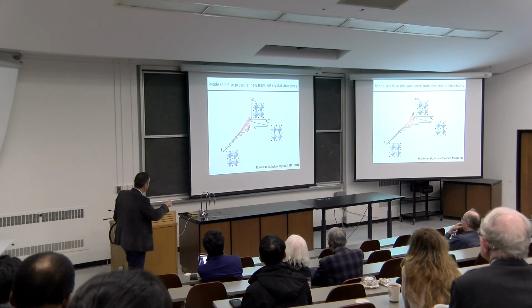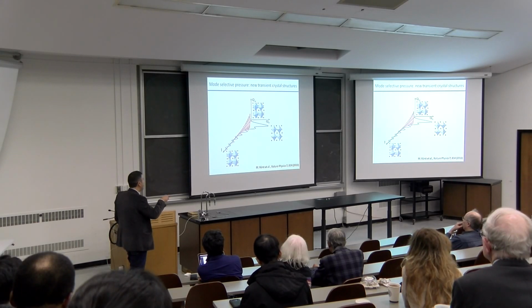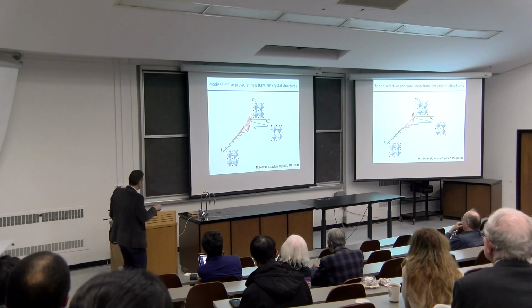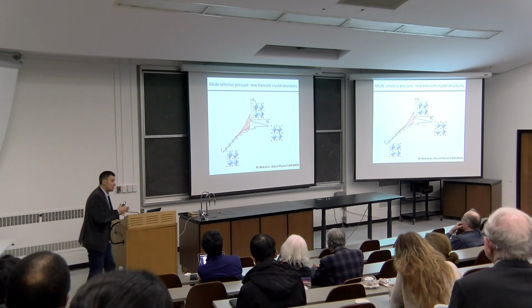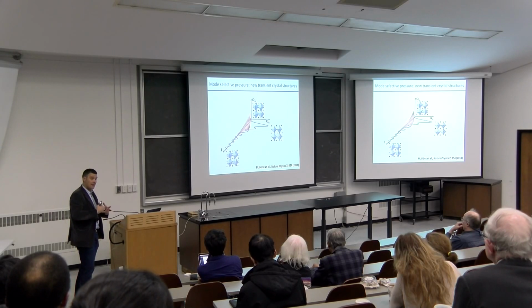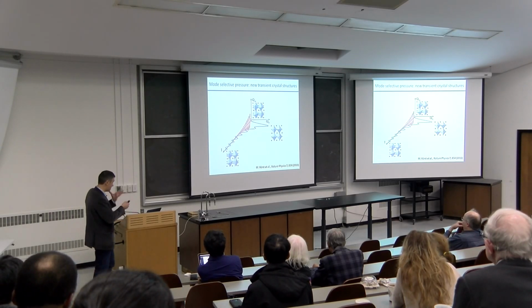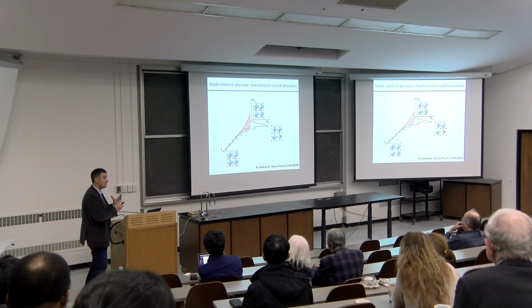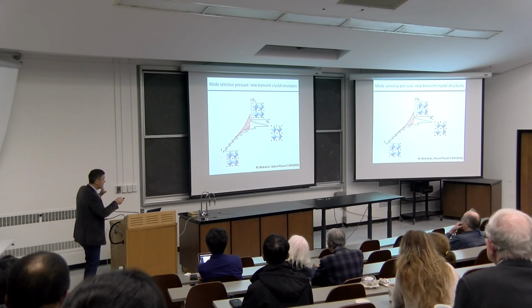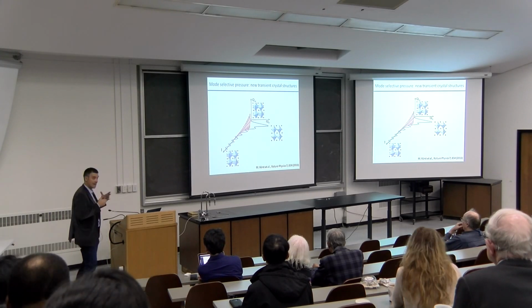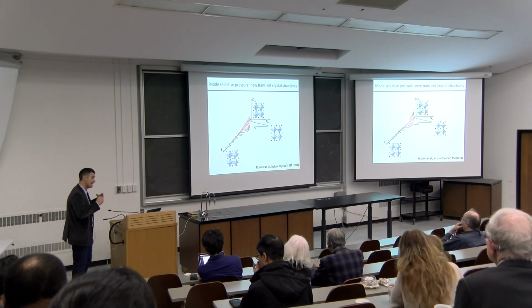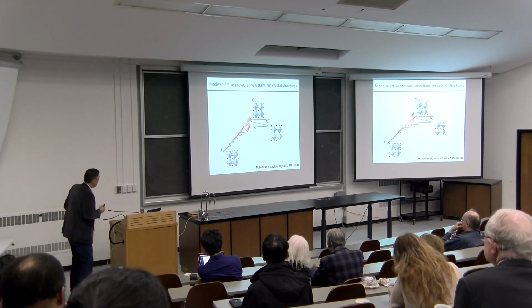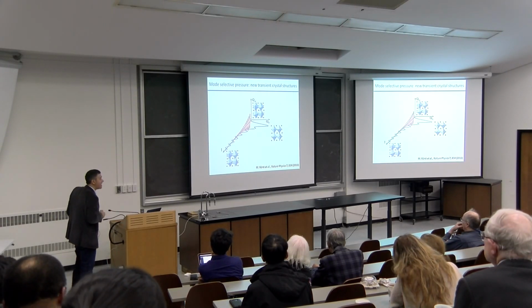The reason why this is very interesting is that now I can think in this term to a situation. This is time now. These are two coordinates. This is my driven mode, which, as I told you, shakes. And then there's going to be a force onto the second mode, which has finite area. So this is a pressure term, but it's a pressure term that doesn't change the volume of the system, because these are optical phonons. And it's a symmetry selective pressure term. There's selection rules that tell me how this mode can couple to that. And so in principle, I can deform the lattice in a surgical way and try to create transient crystal structures.